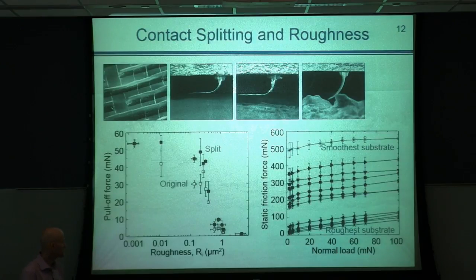And what you see here is the result of measurement of friction against several rough substrates. First of all, we can see that increase in roughness results in decrease in friction forces, which is expected. And we can also see that frictional forces measured with wall-shaped microstructures are extremely high, with a ratio of friction to normal load of over 100. You can see it here for low loads of 2 or 3 millinewtons. We get friction force of about 500 millinewtons, which is very efficient and large friction forces that may find applications in different fields.